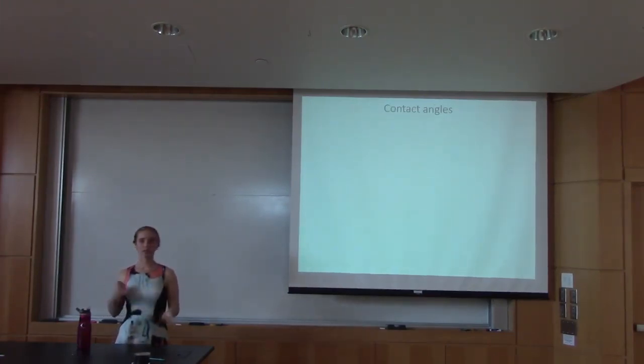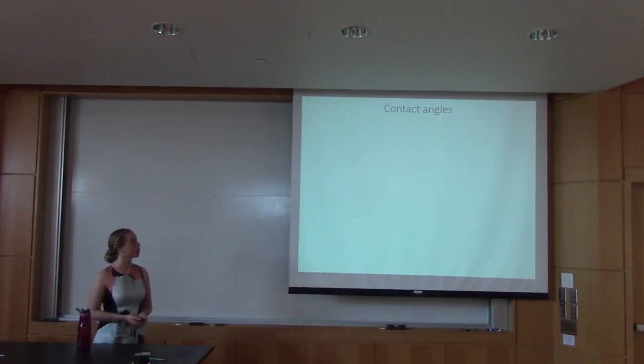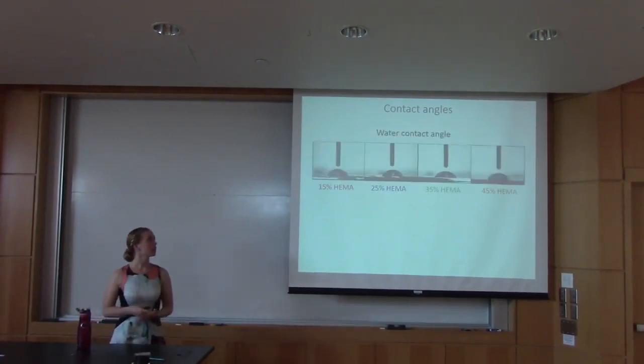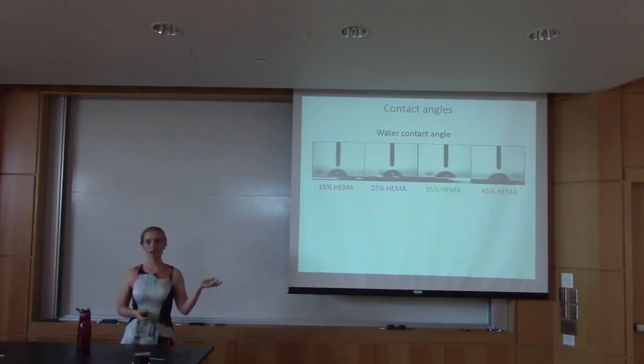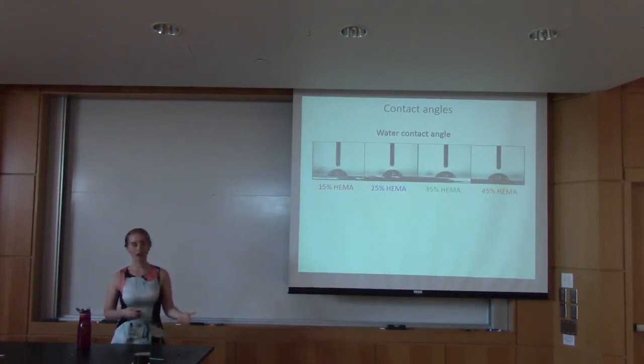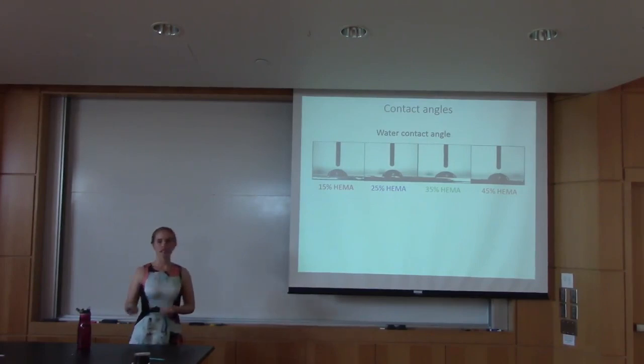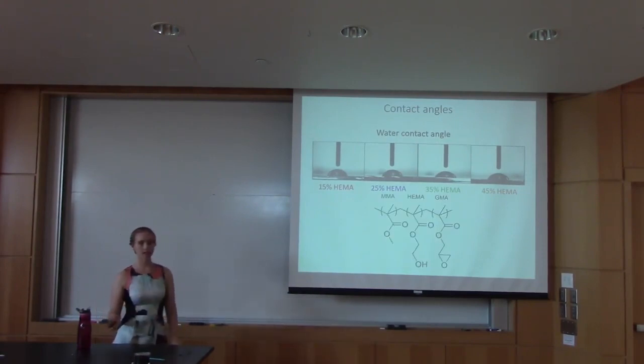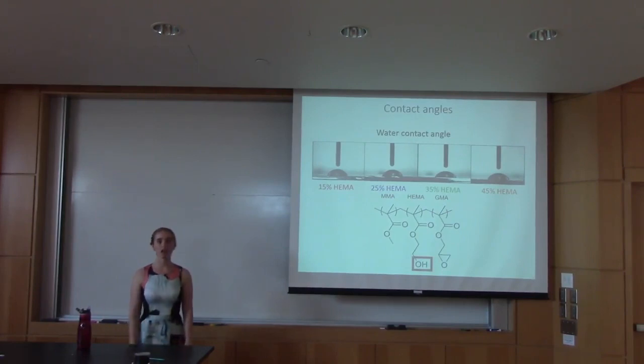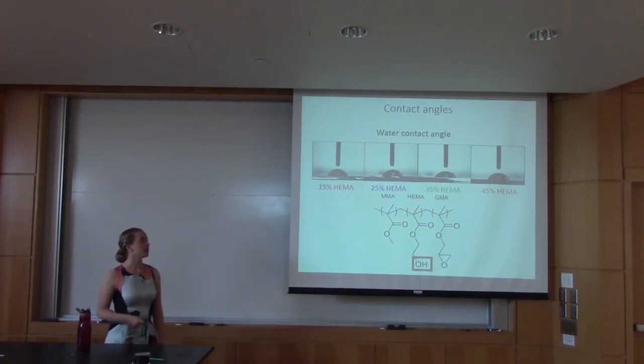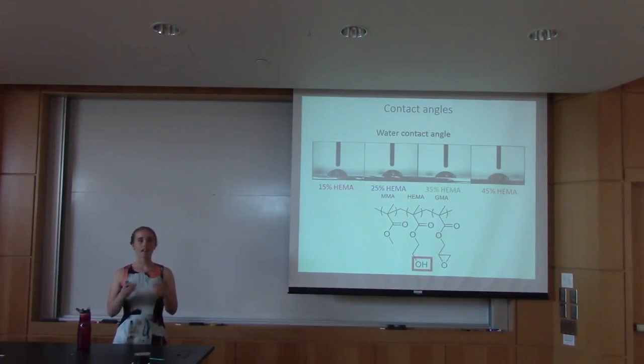So with that, we're going to go to some of the data that I took throughout this for our contact angles. And so we have water contact angle. We are increasing in HEMA, or the more hydrophilic part of this random copolymer, as we go from left to right. And we are then decreasing in MMA also. And you can see that as you increase the amount of HEMA, you have a much more broad water droplet because it's more hydrophilic. And we can look at the molecule and see this too. So we have that OH at the bottom of the HEMA, which makes it more hydrophilic, and thus when we have a water droplet and it's on a surface with more HEMA, it's much more spread out.